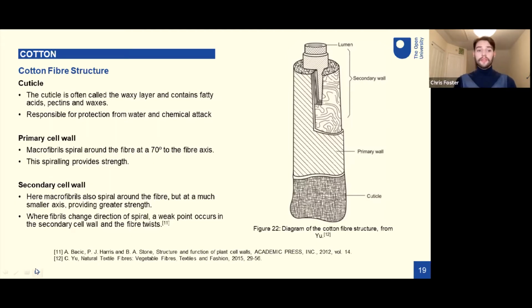The cell walls, this primary and secondary cell wall, contain the macrofibrils, and they actually spiral around the fibre axis. And this spiraling provides some strength for the fibre. The primary cell wall is slightly weaker than the secondary cell wall because the angle at which it spirals around the fibre is greater. This spiraling of the macrofibrils causes the whole fibre to have a kind of twisted conformation, which you'll see in a minute.